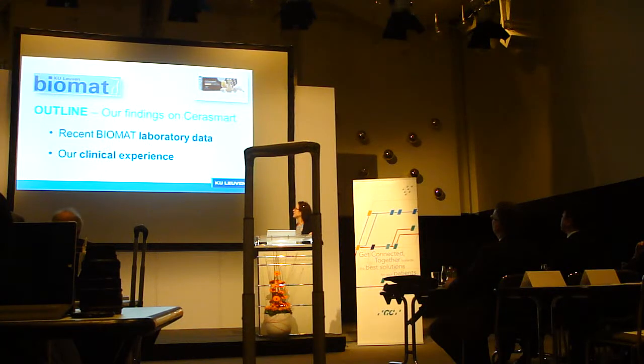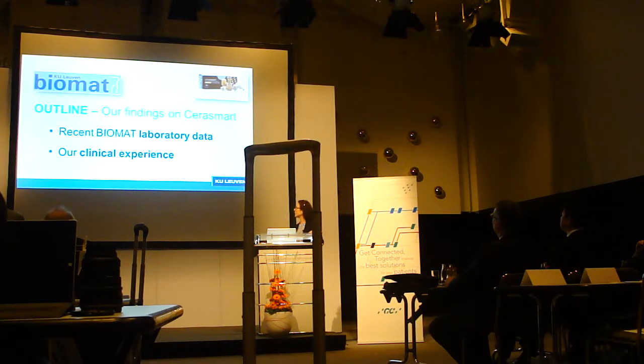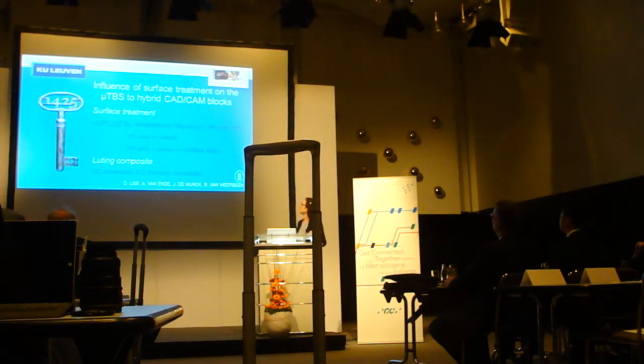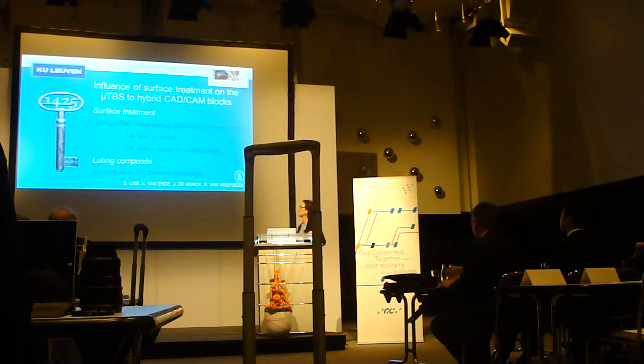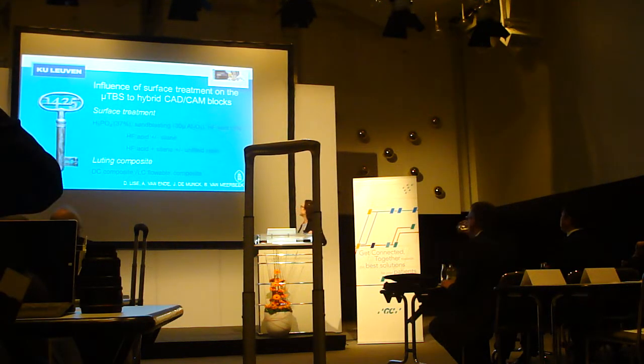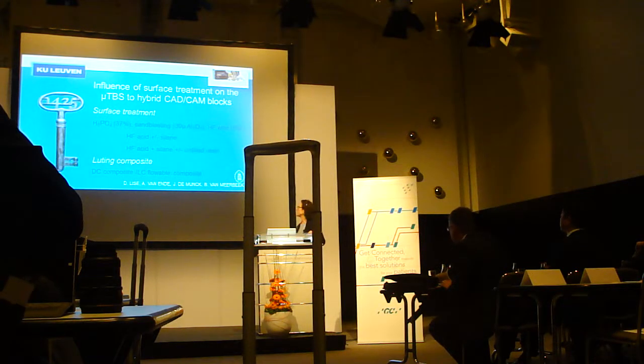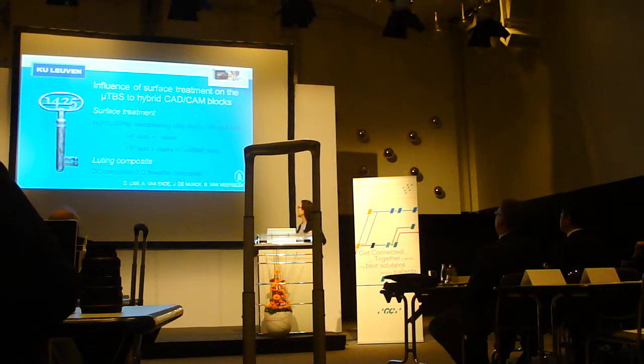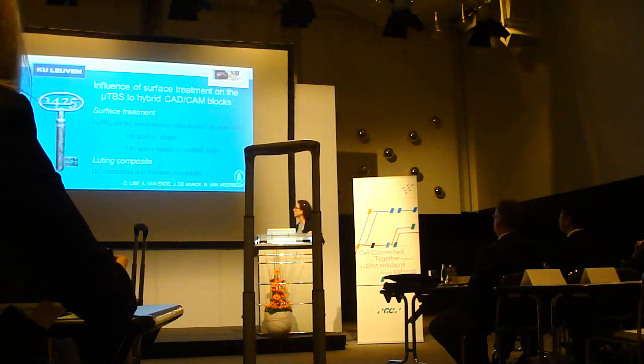What are now our findings regarding the Cerasmart hybrid CAD-CAM block? I will present first some of our laboratory data and next our clinical experience. In the first in vitro study, the influence of different surface treatments on the microtensile bond strength of the Cerasmart hybrid block was evaluated. We had different surface treatments: phosphoric acid etching, sandblasting with 30 micron aluminum oxide powder, and etching with 5% hydrofluoric acid, eventually followed by application of silane and/or application of an unfilled resin. For luting, we used either a dual cure luting composite or a light cure flowable composite.